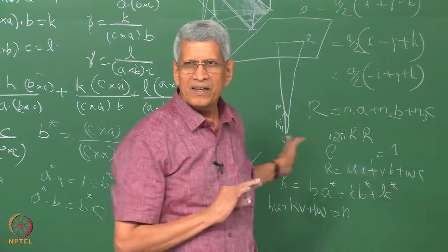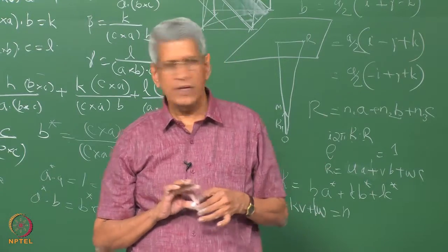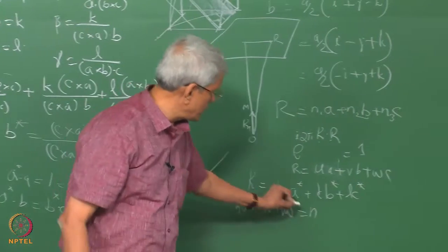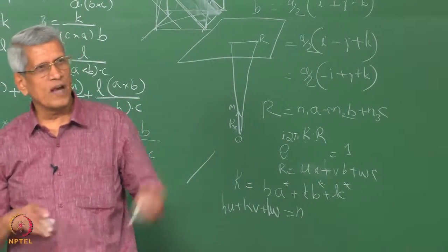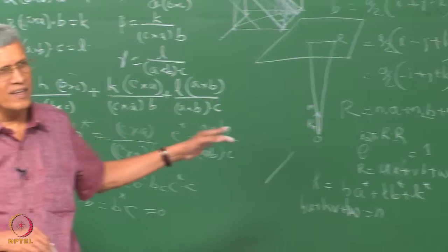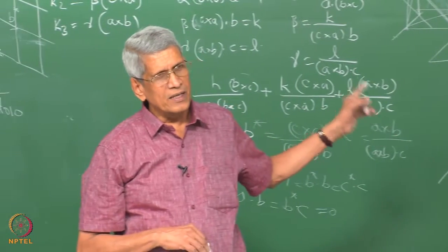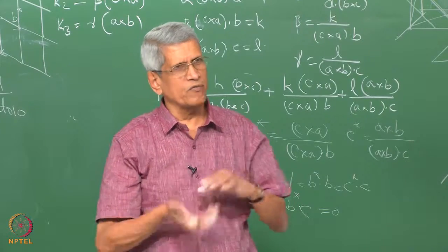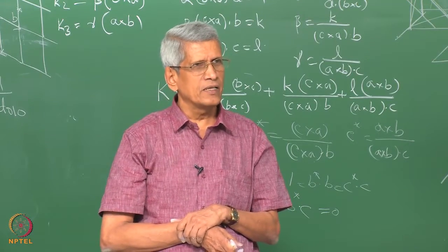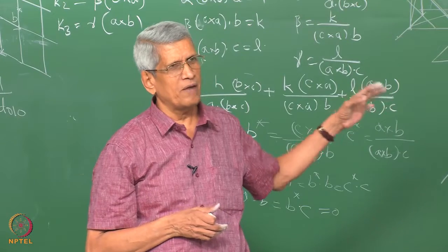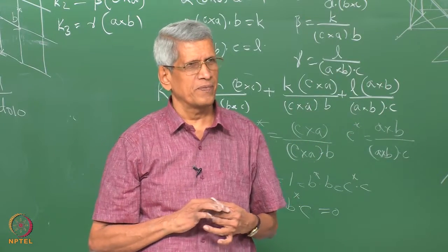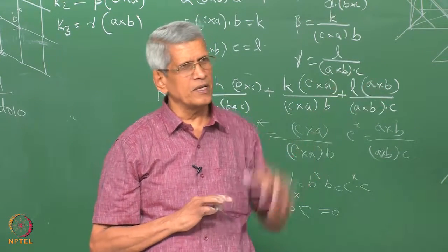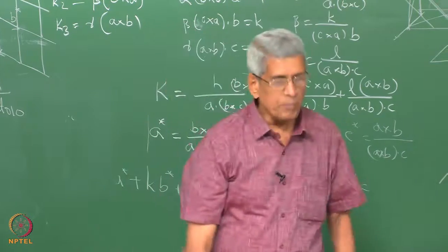That is why this expression turns out to be so. When this expression equals 0, that is what we call the zone law. If we use this law to look at different reciprocal lattice planes and are able to get that information, the complete crystal structure information will be available from the 3-dimensional lattice. That is, the Bravais lattice can be reconstructed from this. We will stop here now.